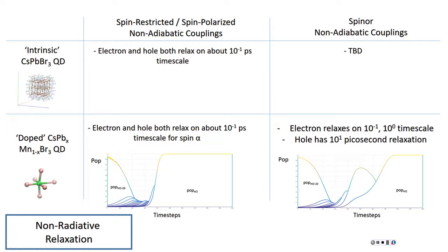They're actually a little bit different. So they show a little different relaxations, even though the energies of the bands are about the same. I know, it's kind of weird. So for the spin polarized, if we excite a hole deep into the valence band, about 20 states, that's going to be on the perovskite. And then the population is going to decay.